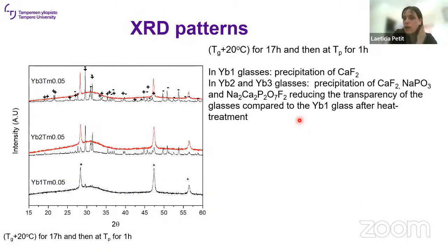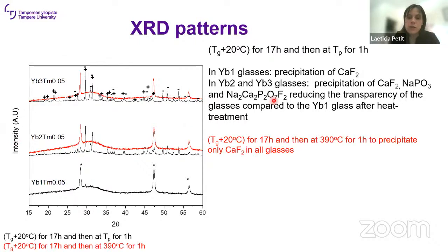We used XRD to try to understand what's going on. At first we did the heat treatment at Tg plus 20 for 17 hours and then Tp for 1 hour, and the XRDs are in black here. For low concentration of the rare earth ions, we have this calcium fluoride crystal, as we did in the erbium-doped glasses. But when we increase the concentration of ytterbium, then we have some other crystal growing. So we had to reduce the growth temperature to 390 to grow only the calcium fluoride crystal in the glasses.